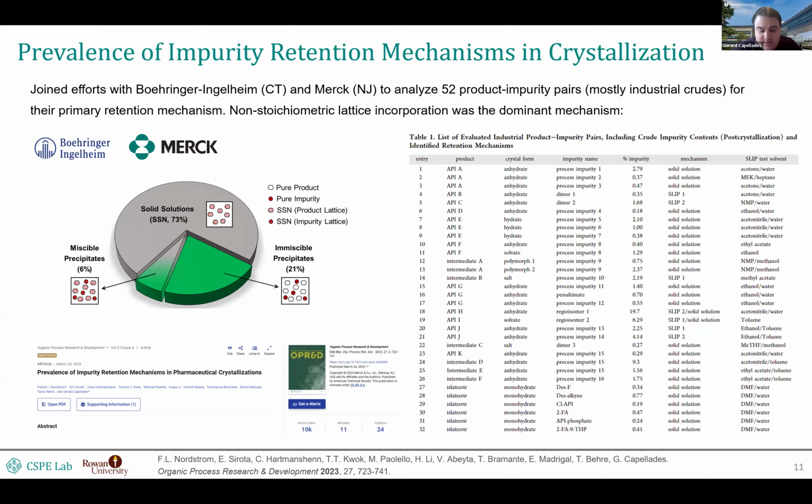I think they are always going to form. We're still trying to figure out the thermodynamics, so take this with a grain of salt, because we're still hypothesizing a lot about this. But the formation of a multi-component crystal is thermodynamically favorable. Even though there are enthalpy penalties to the incorporation of impurity within the crystal, entropy likes having the impurity inside the crystal lattice. It's not going to allow something that's completely pure.